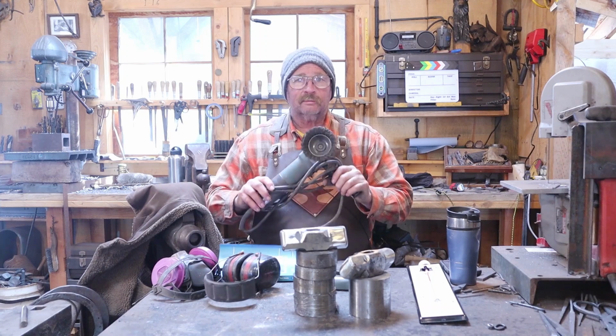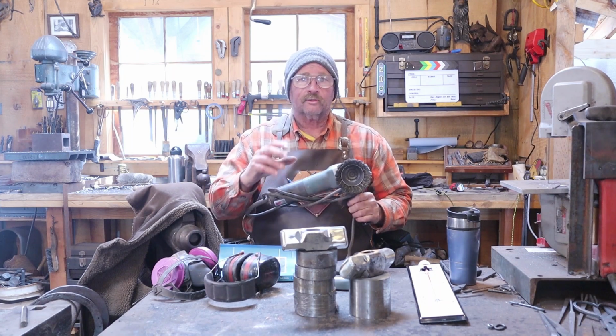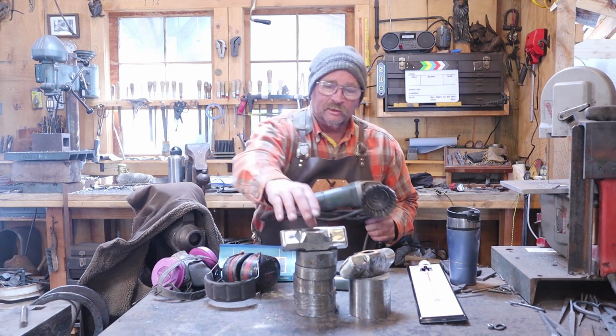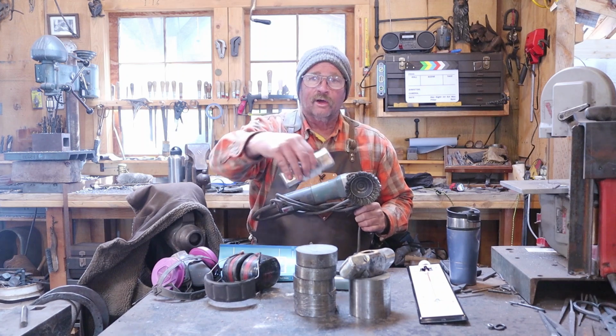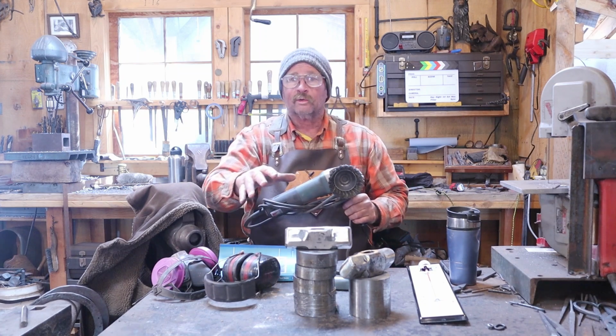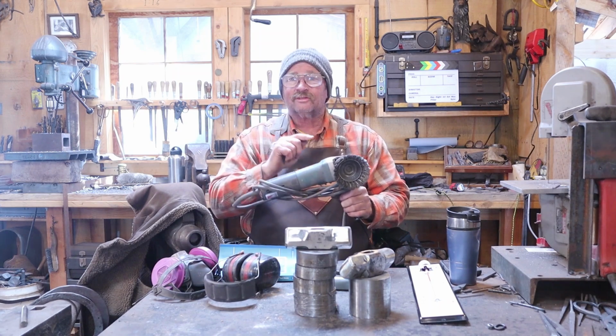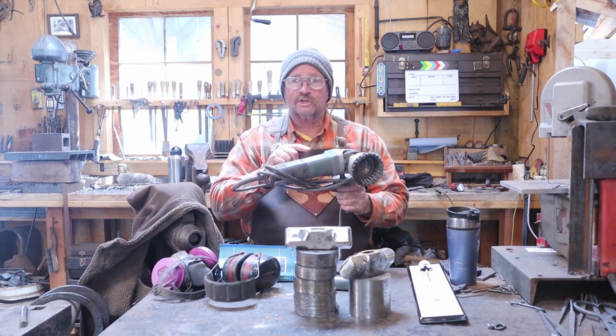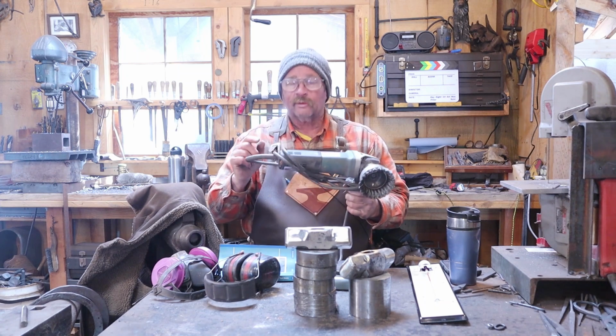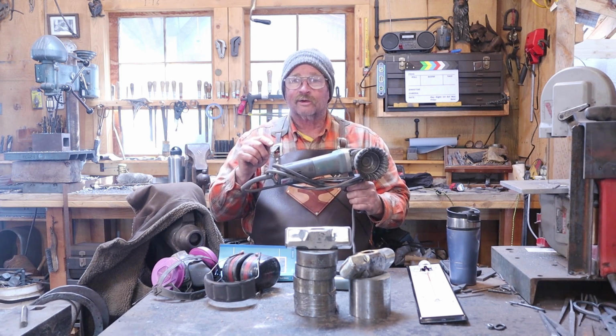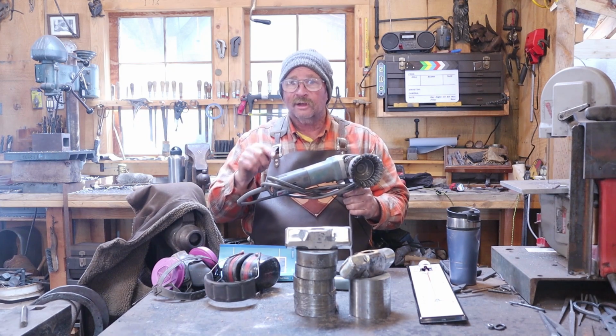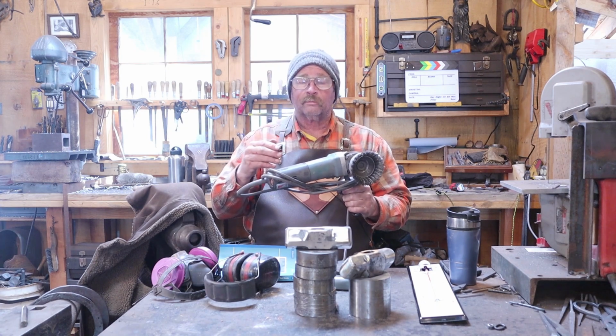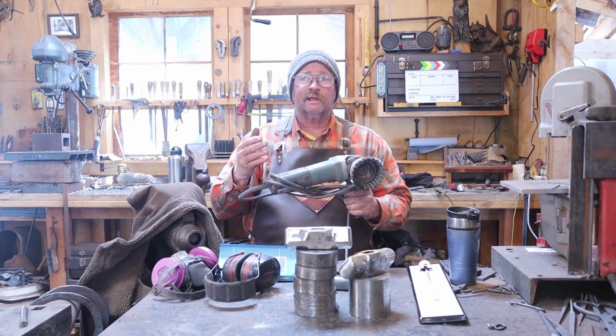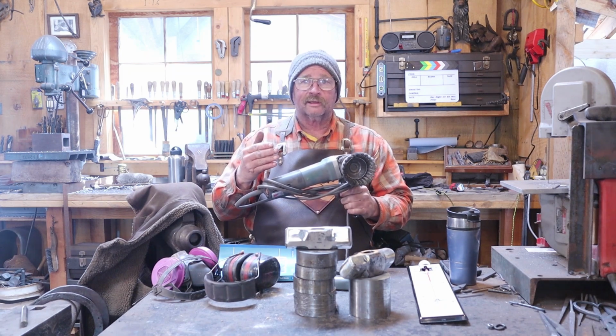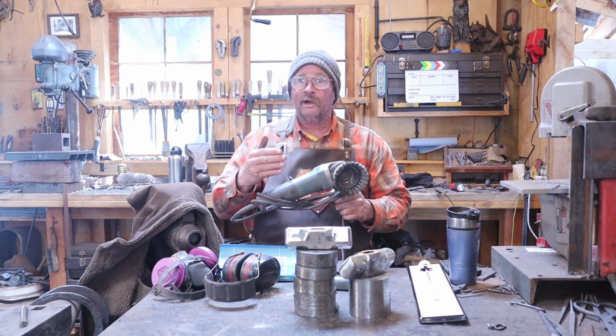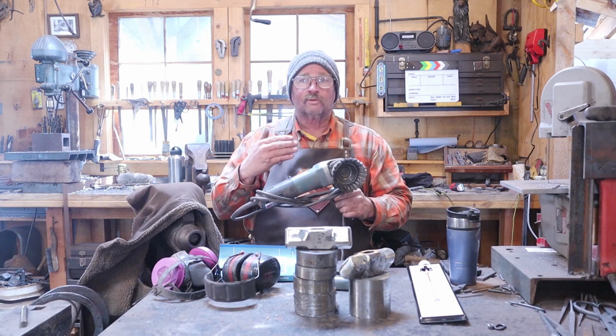Now, cup brushes can be very dangerous. I'm going to lock a drift in my vise, and I'm going to just put this over the drift so I can't launch it across the room. I don't have to try and hold it with a pair of tongs. And this is actually a sander polisher, not an angle grinder. So it has an adjustable speed. I can turn it down to about half the speed of an angle grinder. That makes it safer to use than a wire brush on an angle grinder. Be really careful if you're going to try something like this, but the finish from a power wire brush on hot material is quite nice.